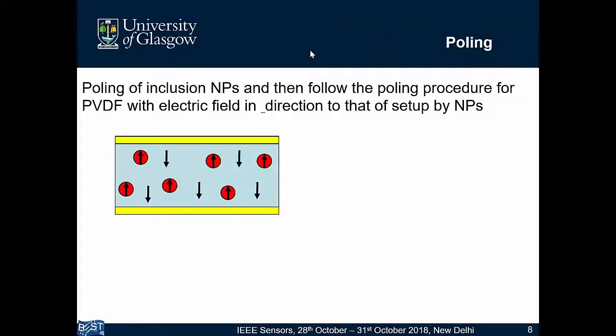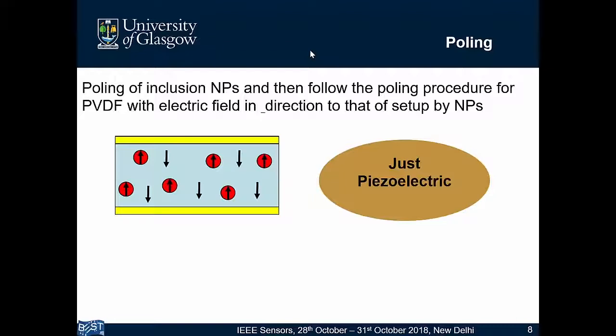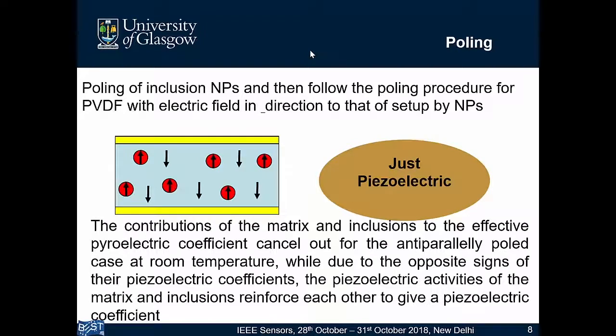To obtain the piezoelectric property from any polymer based material, we need to pole it. Poling means we have to apply an electric field across the material to align the dipoles. This property has been exploited to suppress the pyroelectric response. Since they both have opposite dipoles, we performed a two-step poling. First we pole the nanoparticles, and then we pole the polymer, so that we just get the piezoelectric, and by poling we cancel the pyroelectric property.